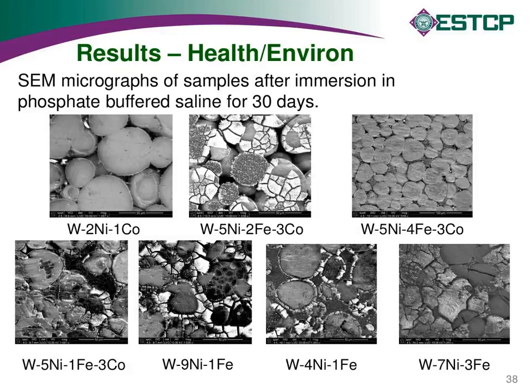Moving on to slide 38. This shows some of the corroded samples where what I'm calling the tungsten 2 nickel 1 cobalt shows just massive dissolution of that matrix phase, and in any of the other iron-based alloys, you did see evidence of formation of that passive iron oxide, and so that suggests that we can move away from the 7 nickel 3 iron alloy to some other combinations. I guess this can be kind of a long story, but to make a long story short, there's evidence that you can improve the engineering properties, so the ductility and toughness of some of these alloys, by reducing the nickel to iron ratio. Sorry, increasing the nickel to iron ratio.